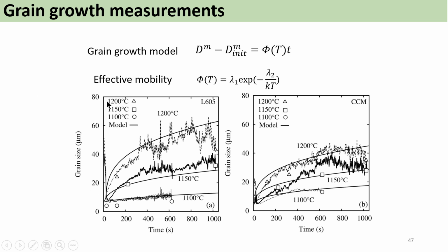Here is an illustration of the result that we have obtained. We have three different holding temperatures: 1200 degrees, 1150 and 1100 degrees. And we have a large grain size, rapid grain growth, at high temperature, whereas very small grain growth occurs at 1100 degrees. These are two different alloys. One is called L605 and the other one is called CCM. Those two alloys show very different growth rates in those same conditions.